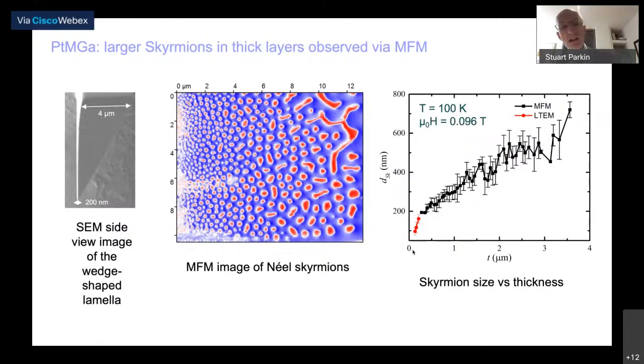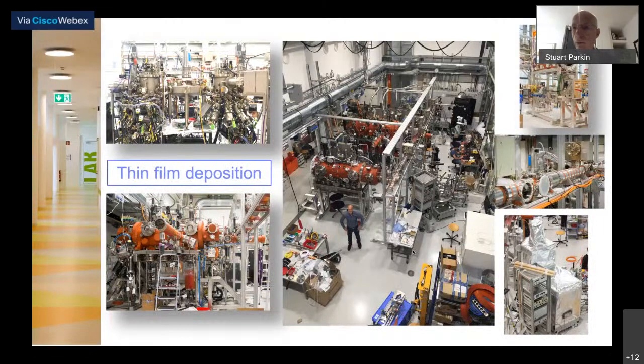And as we vary the thickness in this lamella from the left to the right, we find that the size of these Néel skyrmions changes dramatically, as you can see from the size of these red blobs. And the size increases from 100 to more than 600 nanometers as the thickness of the lamella is increased to 3 microns. So we've demonstrated the possibility of tuning the size of these objects by tuning dipole fields, which is very interesting technologically.